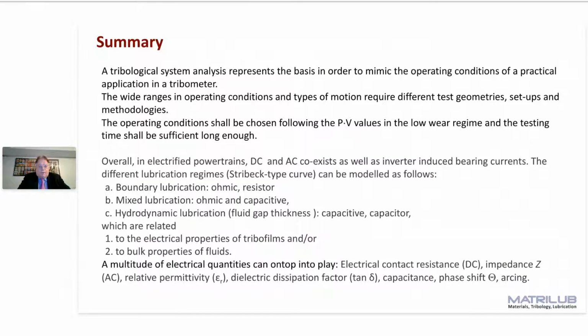So to sum up, a tribological system analysis represents the basis in order to mimic the operating condition of a practical application in a tribometer. And the wide range of operating conditions, the wide range of types of motion require different test geometries, setups, and methodologies. You must not exactly meet the operating conditions by value. You must be at least in a range that you can be sure that you are, let's say, in the lower regime by means of temperature and PV values, and you should test sufficiently long to be sure that you are not in the running-in phase, which always is the high-wear region.